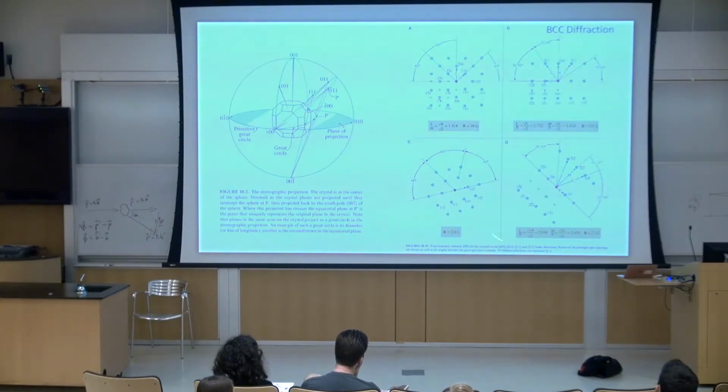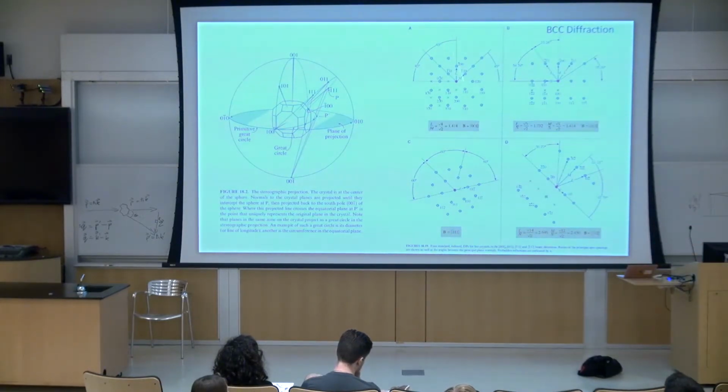We often have tables of generated sample diffraction patterns. So I know if I look down 100, I expect to see a 110 spot and a 020 spot, but I won't see a 100 spot; that's forbidden. The only time I'll see a 100 spot is if I have superlattice ordering within the cell, because it got lost by constructive interference.